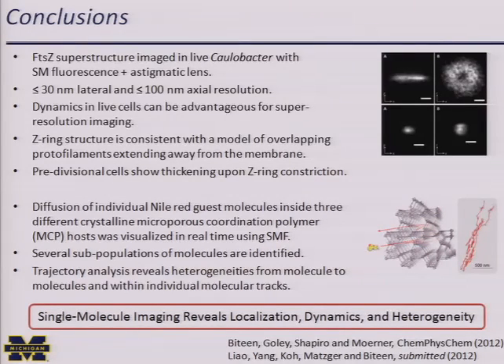Going back to the FtsZ story, what we were able to do was get the FtsZ structure in live cells in 3 dimensions using single molecule fluorescence plus an astigmatic lens. Our resolution was about 30 nanometers in the lateral direction and about 100 nanometers in axial resolution, though I should point out that the diffraction limit in Z is much bigger. It's on the order of 2 microns, and so 100 nanometers actually was a surprise.